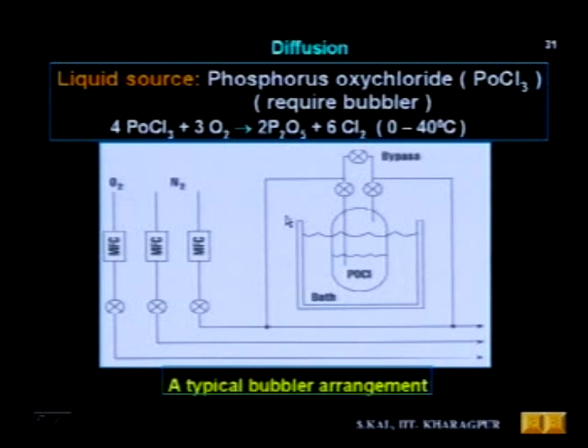And in the diagram you can see that some gas flow arrangements are also kept, and MFC is known as mass flow controller, so that can regulate the gas flow into the bubbler or into the diffusion chamber. After the MFC, you can see some valves are there. Different gases will have different paths. This is the oxygen gas flow path, and nitrogen is here. Similarly, you can use the argon gas flow path, or sometimes you require nitrogen and some other dopant gas flow, etc. Anyway, the nitrogen is flown into the POCl3 bubbler, and the bubbler is kept in a bath, and that bath is used to maintain a constant temperature of the bubbler.